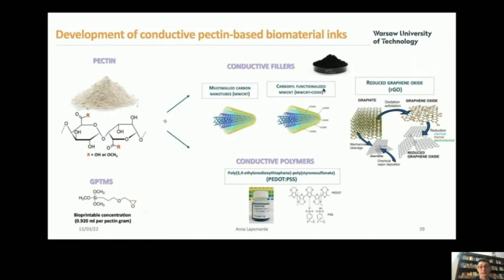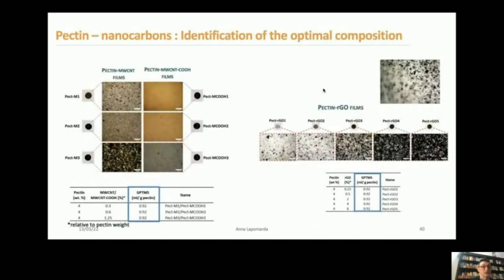The other approach that we developed in collaboration with the Warsaw University of Technology was to try to combine pectin with conductive fillers such as carbon nanotubes, PEDOT or graphene. As you can see here, combining this material with different structures such as carbon nanotubes or graphene, increasing the quantity, initially the film changed color, became darker, because obviously we increased the concentration of the carbon nanotubes or the graphene.